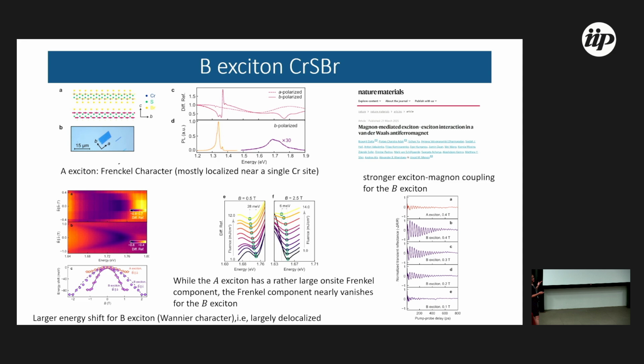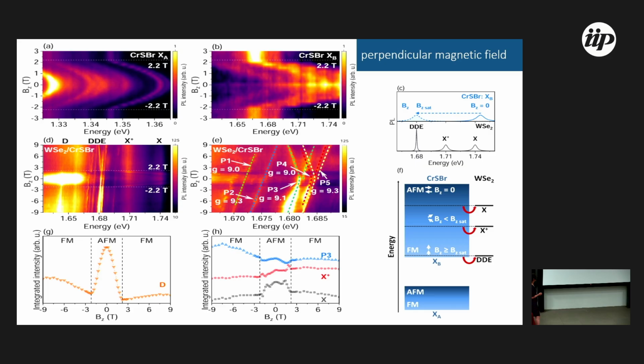Why do I say this? Because this B exciton has an important role in my sample. I will show why very quickly. This is the A exciton and the B exciton that change more. Here is 16 millielectron volts, and here is more or less 8 millielectron volts. This is the color code map for perpendicular magnetic field, so the B is parallel to the c-axis. We have clear changes here when we have the phase transition, but we have a different result here for the exciton and trion. You can see that it does not occur at the phase transition.